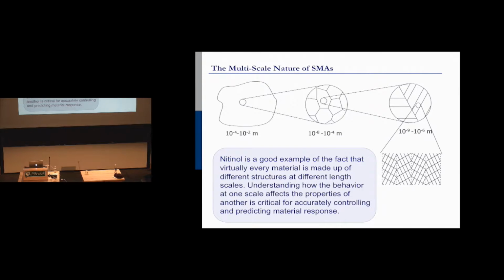That can be inside of a grain where some of the grain is transforming and some of it isn't. Turns out that transformation in grains can be very heterogeneous, where some of the atoms can actually transform to the monoclinic and some just stay as cubic. And so that'll change the stress state in the grain. So you're loading, and that changes the stress state in the grain, and that changes the transformation in the grains all around it. And then at the mesoscale, you have the localized Lüders bands that are propagating through the material. And then on the macroscale, you've got this really weird stress-strain curve showing the hysteretic behavior. So there's a lot of stuff going on in this material at different length scales.